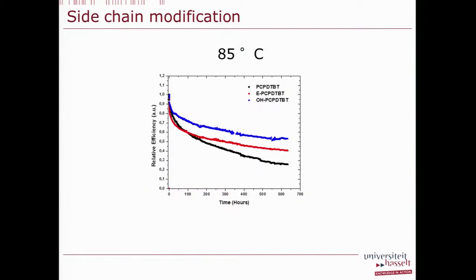How do the initial results look like? What we see here is measurement 650 hours at 85 degrees Celsius. Here we have the normal, in black, the normal PCPD-TBT, and here the two ones with a sidechain modification. And you can clearly see that with the sidechain modification, we have an important improvement.